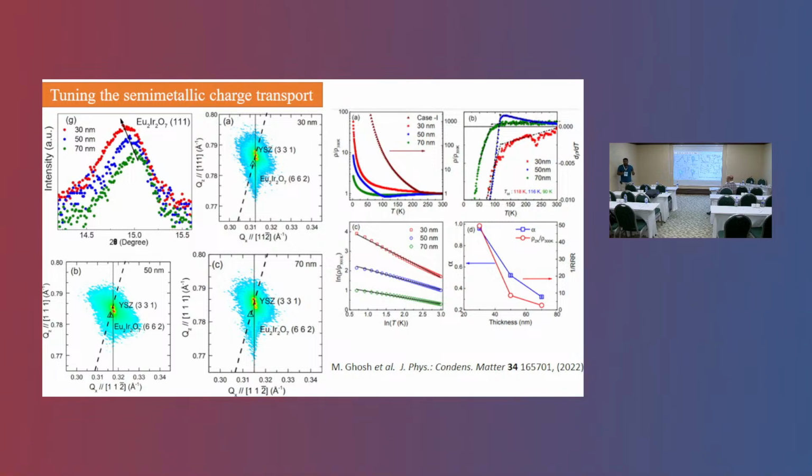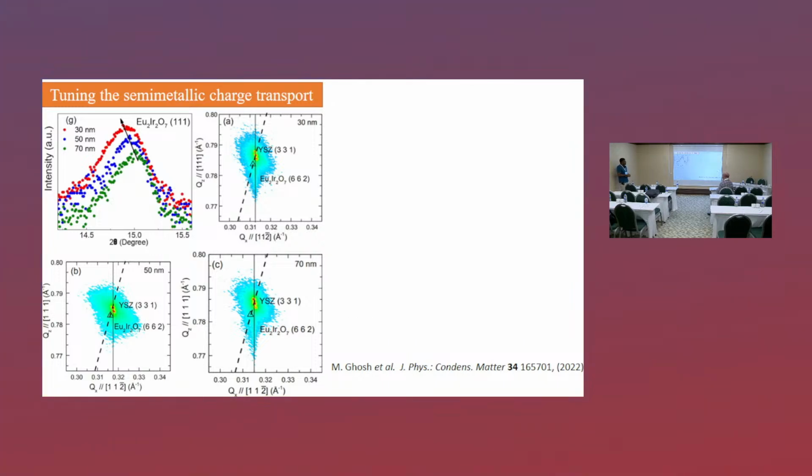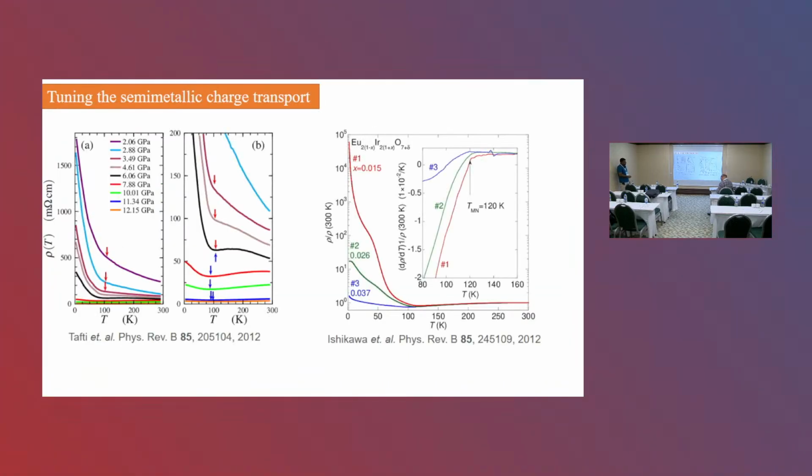Magnetoresistance trend and behavior will be similar, but the absolute value can decrease or increase. Because of the Ir, when you have an impure sample the spin network will be disjoint or something like that, so the value can decrease and also increase. So this compound is very much stoichiometry sensitive. Even people who have done single crystal studies are not able to get this. Here they are getting a nice transition, but if you see this other study, they are not getting a nice transition.